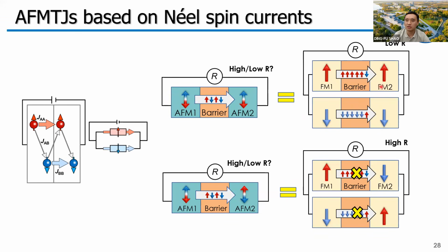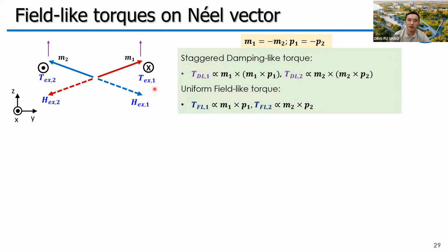across the barrier to the right electrode, it can generate a staggered spin polarization on the two sublattices, which means in the LLG equation, the M1 and M2 for the two sublattices are opposite, and the generated spin polarizations P1 and P2 for the two sublattices are also opposite. In this case, the damping-like torques, M cross P, for the two sublattices are staggered, which will not influence the perfect antiparallel state of the two moments.